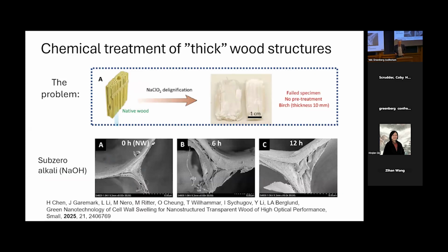So this is very recent work addressing the problem that delignification could be an interesting possibility to create new wood materials. A problem is if you try to do that with thick structures, you end up with pulp at the surface and no chemical treatment in the center. So what we have done is use sub-zero alkali. If you look at the left-hand side image, you have a very thin cell wall, whereas with the same scale bar, you have significant swelling of the cell wall. And this is dramatic, several times the original thickness. It means that we have a large amount of nanoscale porosity, which opens up possibilities for manipulation of the material.